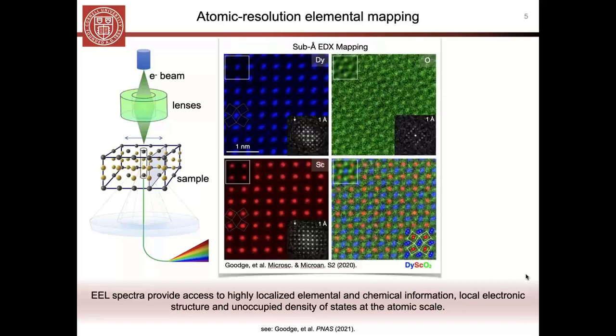This is something that I think a lot of people are familiar with the use of EELS for, but it's worth pointing out that, especially with instrumentation improvements outside the EELS spectrometer, for instance with X-ray detectors and other microscope improvements, EDX elemental mapping is approaching basically the same levels. So we can now also atomically map elements with EDX. And in fact, the analysis for this kind of mapping is in many ways more straightforward than using EELS for these same kinds of experiments.